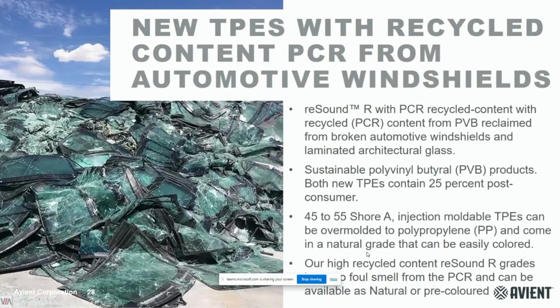And the last, but not least, I'd say, is our most recent family of products of TPEs with recycled content. And as you can see the source of the recycled content. In this family of reSound R, we use PVB, that is reclaimed from broken automotive windshields and laminated architectural glass. And the really good point here is that we can achieve the circularity for this product. That is the inner layer in the windshields that gives the right properties in order to avoid a break of glass parts within the vehicle. That could be a safety issue.